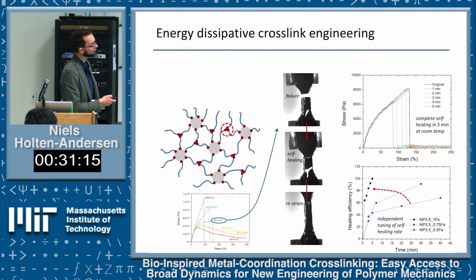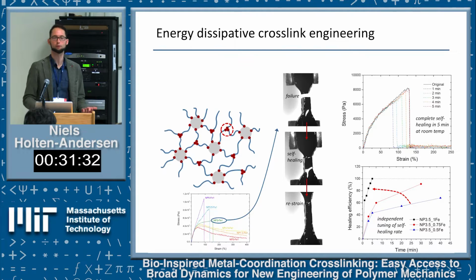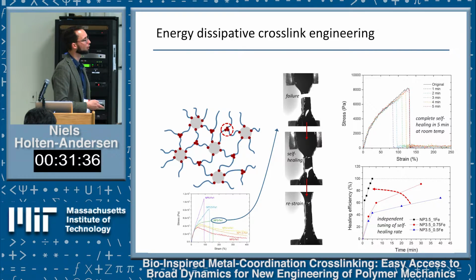Our early data shows that for these hybrid materials, as a function of how long you let the material recover once you put it back together—at room temperature, we're not heating them, we're not applying pressure, we're just letting them touch each other—within 5 minutes, the initial mechanical properties have recovered completely. That's again going back to what we were excited about with the muscle material in the beginning.